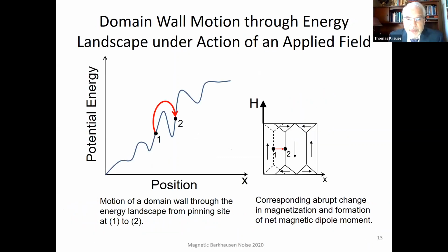So then what is Barkhausen noise, or how does that come about, or what happens when we apply a field? If we apply a field along a crystallographic 100 direction, what we get is the 180-degree domain wall moving due to the force applied by the field, which basically increases the energy, the E dx, I should say. That force causes the domain walls to move, but they don't move very smoothly.